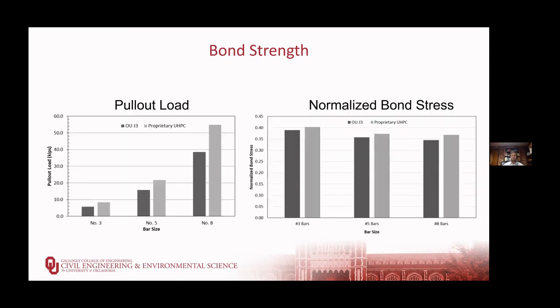We compared bond strength with a proprietary UHPC as well. So OU materials are shown in dark gray, a proprietary UHPC in light gray. And if we look at it just in terms of the pullout load for our pullout test, it looks like the proprietary UHPC has a much higher strength. But if we normalize that based on the compressive strength, we get very similar performance to the proprietary materials in terms of bond strength.